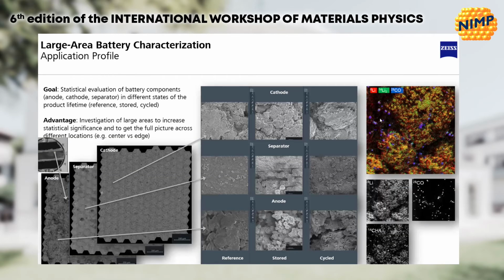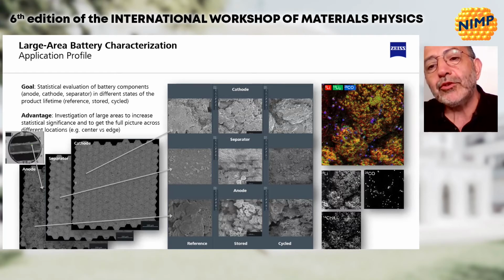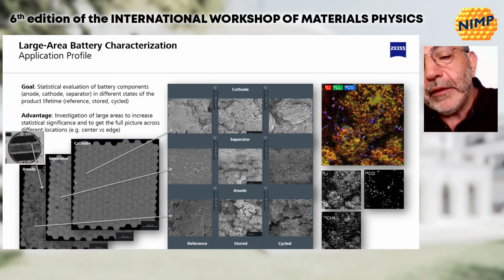And in the end, you can even perform analytic composition. In this case, we are correlating mass spectrometry analysis on the colored image, showing distribution of lithium isotopes, different types of isotopes. In this case, isotope 6 and isotope 7, which play an important role in the development of lithium batteries, and put in the full context of the battery, in this case in 2 dimensions, of several square millimeters up to a square centimeter.